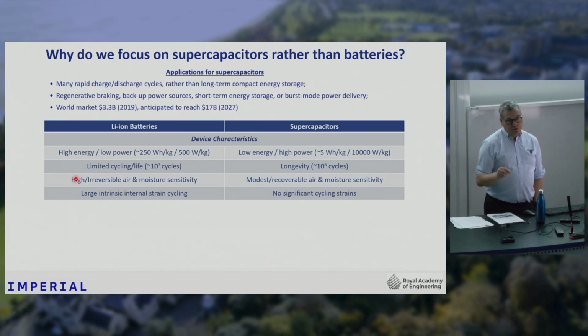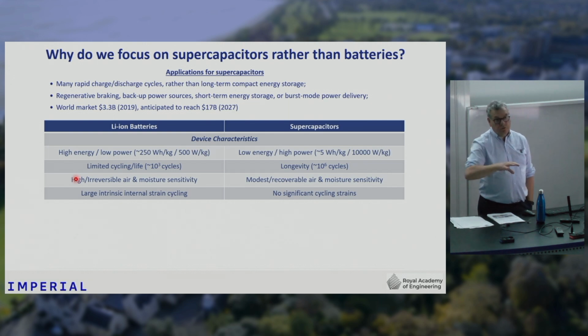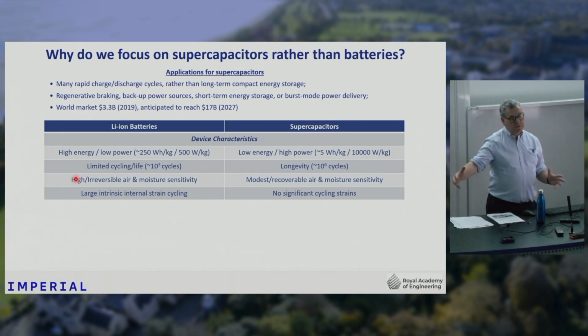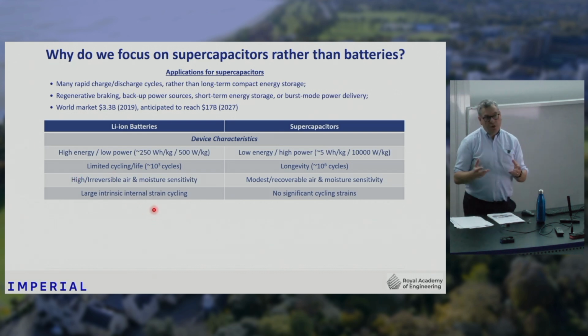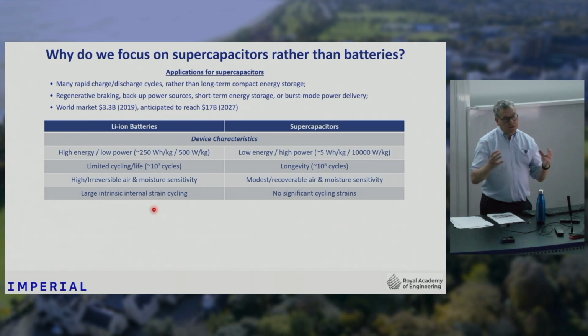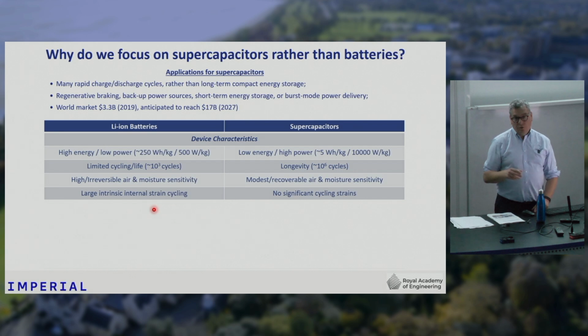Battery materials are very sensitive to moisture, and even oxygen in the air can permanently degrade battery materials. So from the perspective of making a wing, for instance, out of a battery material, that presents some very big challenges. Supercapacitors are less sensitive to moisture. We saw this as an easier route to get industry interested in this technology, because we can potentially get rid of the moisture once we've made the device. Another problem with batteries is that when you charge, the material itself expands. You're moving lithium ions into the carbon, and that pushes the carbon planes apart and makes your material expand. If charging and discharging cause the material to expand and contract, and you want that material to be your mobile phone casing, for instance, that's going to present some challenges. That's not an issue for supercapacitors. There's no expansion or contraction during charging.